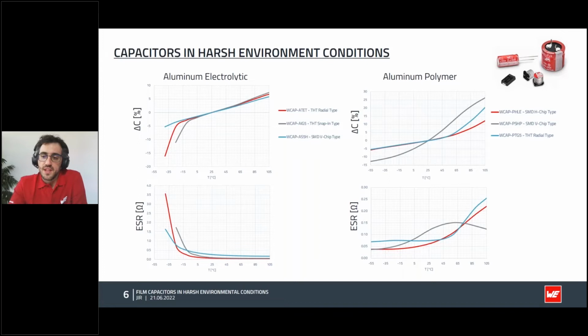As you can see, capacitance drops significantly in temperatures under zero. But more important, the ESR increase makes them very impractical in that range. On the other hand, they show very promising characteristics at high temperature, especially the decrease of ESR. Sadly, the electrolytic will dry faster at higher temperatures. So we can only recommend to drive these capacitors at the coolest possible.